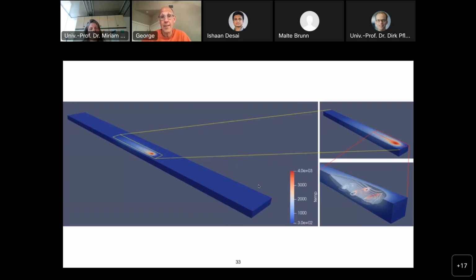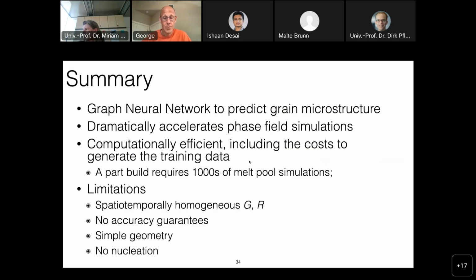So to our knowledge, it's the first time that this technology enables full part microstructure prediction using this neural network. So in summary, we now have a graph neural network for 3D. The ideas we use in 2D are extended to 3D, but you're introducing the graphs. It's extremely efficient, including the cost to generate the training data. As I said, a part requires thousands of melt pool simulations, or if we have 100 samples per melt pool, we're talking about 100,000 phase fields that will take basically months to do the calculation, whereas we can do it in days, essentially, with the graph neural network.